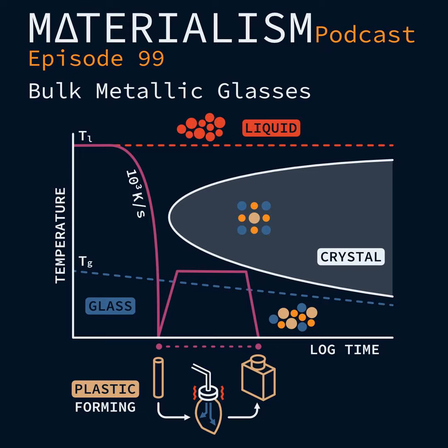Yeah. First of all, entropy is not the issue. It's not the issue in the high entropy alloys, and it's not the configuration entropy. Even high alloy steels have comparable entropy, right? Yes. And actually, in metallic glasses, this was one of the shockers, right? When you actually measure the configuration entropy, it is very, very low. It's particularly low. And this goes back to Andrew's question about the liquid. So the liquid orders so much, enthalpy or chemistry always seems to win, right? You cannot beat it with entropy as we thought in the early days of high entropy alloys, right?